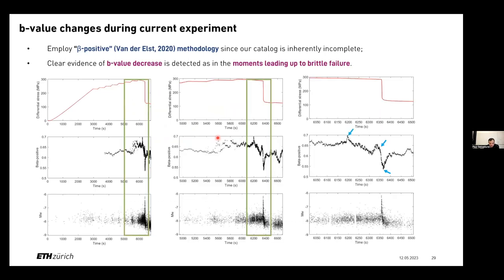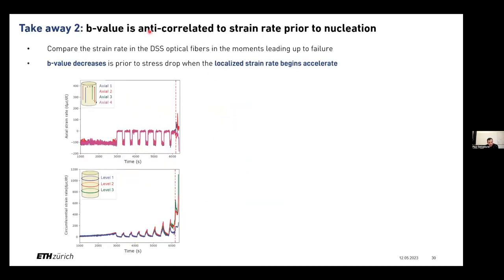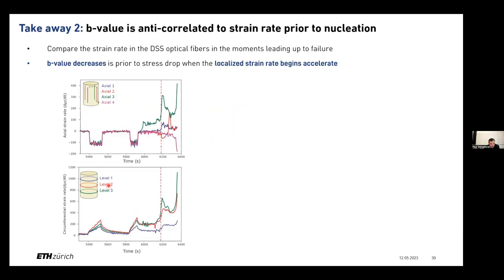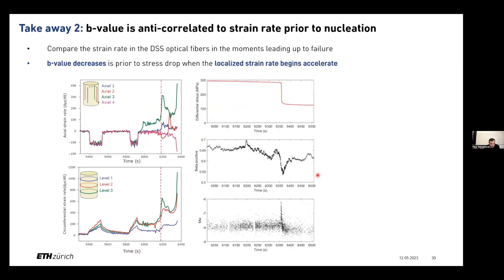So when we move forward with this, what we're trying to show right now is that the B value is anti-correlated to the strain rate prior to nucleation. If we look at the axial strain with the fiber optic sensing, we can see the strain rate. When we zoom in just before failure here, we start to see this runaway pattern in the same time frame that we're looking at here, as this decrease in B value.